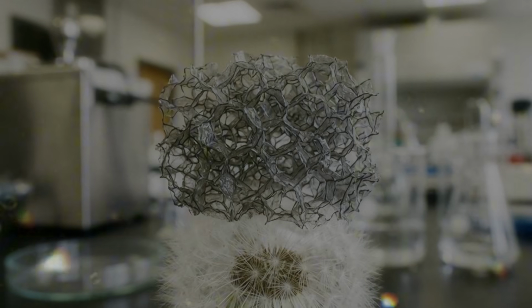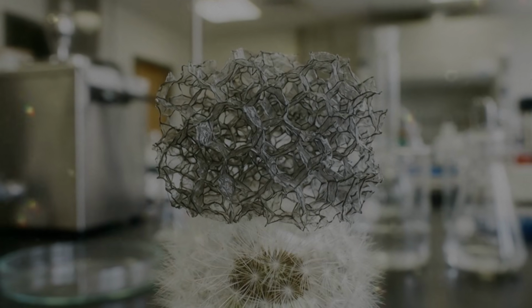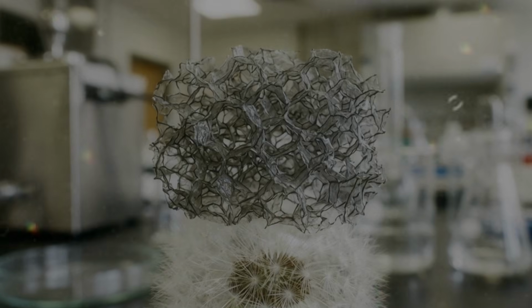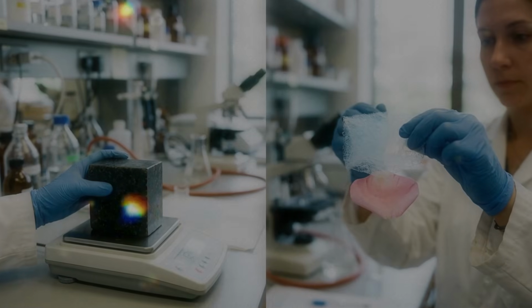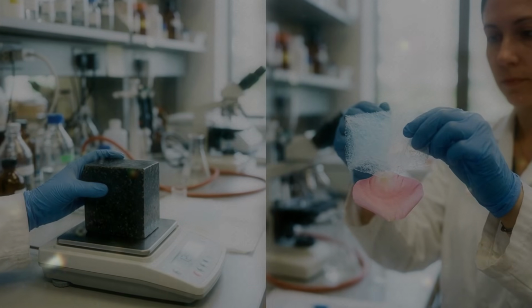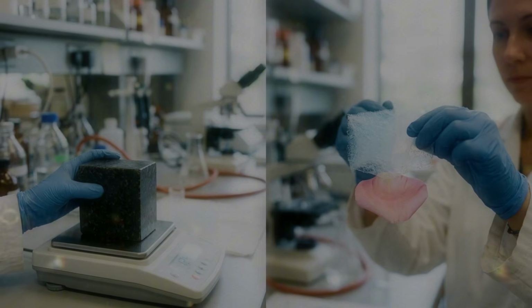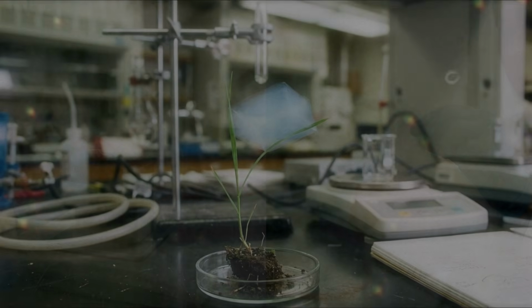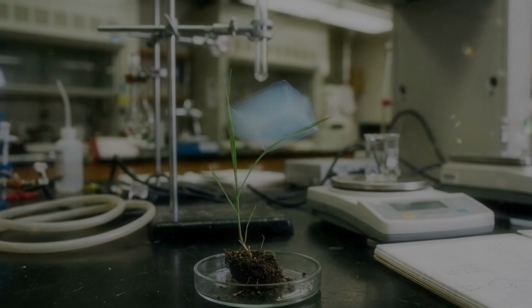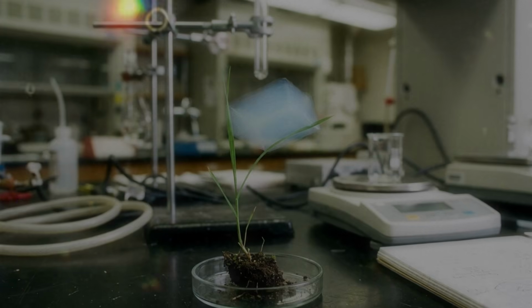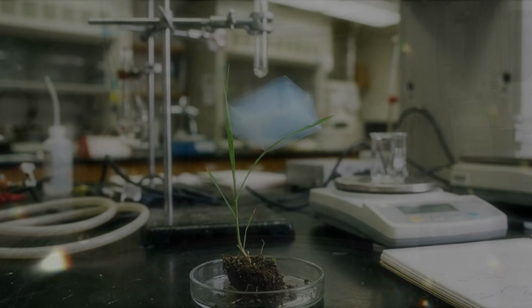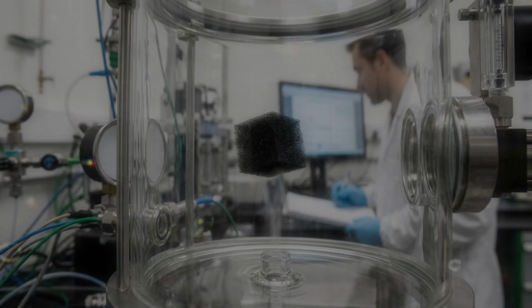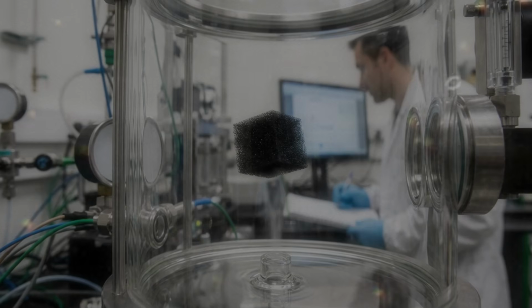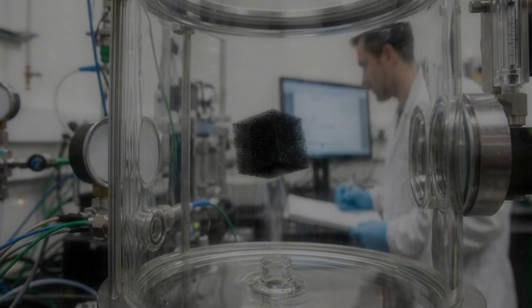After the pores contain a suitable solvent, drying can begin. This is the moment that separates an aerogel from an ordinary dried gel. When a normal liquid evaporates, it develops a curved surface inside each tiny pore. Surface tension pulls along that boundary. In a large, sturdy container, the force is harmless. In a microscopic network made from fine branches, it can become destructive.